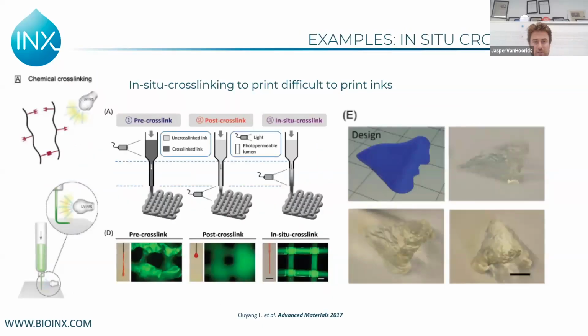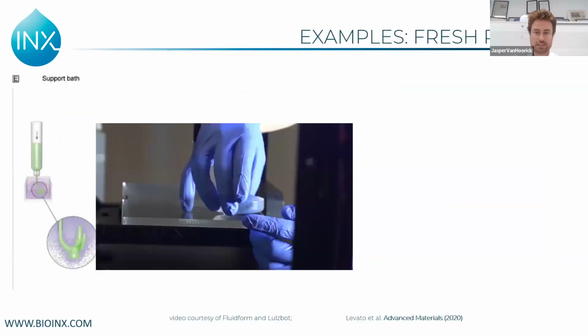And then you can use this cross-linking to have better shape fidelity. For example, you can cross-link it, irradiate it during printing, which is done in the lab of Jason Burdick and was published in Advanced Materials, for which they could get a lot better shape fidelity with materials. In this case, it was hyaluronic acid based.